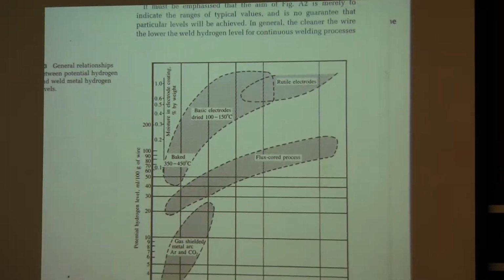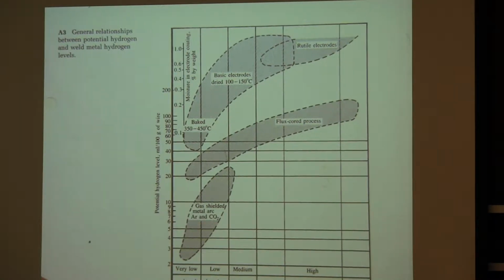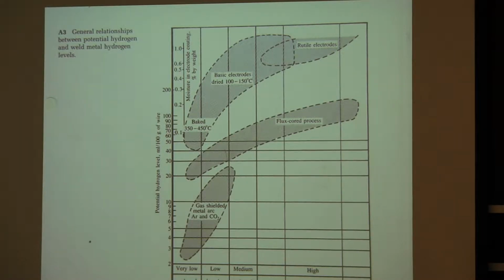Now, I also showed you this before. And this is one of the only places you'll actually see this. It comes out of the Welding Institute book on welding steels without hydrogen cracking. It talks about the weld hydrogen level in milliliters per 100 grams, which is almost the same as parts per million, within 2 or 3%, I think. It works out. And this is the potential hydrogen.